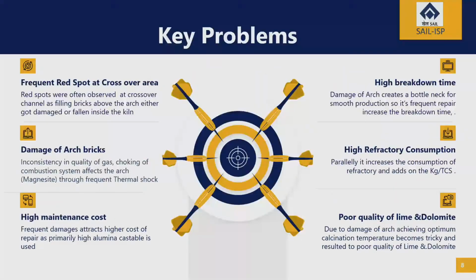Now the main key problems we are facing is that due to the inconsistency of gas and due to the combustion system choking, the refractory usually gets multiple thermal shocks, and due to that, our arch refractory gets damaged and red spots are observed. This also invites high maintenance cost and breakdown time, and it also adds to the refractory consumption in kg per TCS, and as an output we also get poor quality of lime and dolomite.